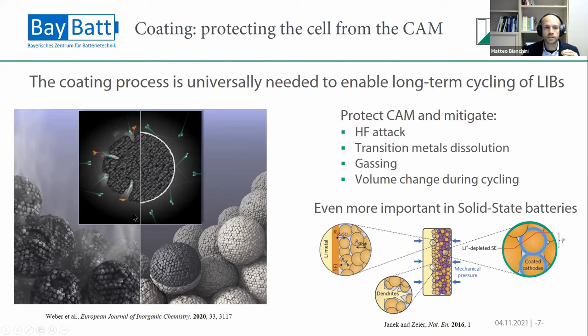And therefore, you need this coating, which is typically just a simple oxide. It could be an alumina or titania, or can be something more advanced like a lithium niobium oxide or a lithium zirconate. And these can have different functions. It can protect the cathode material from HF attack.